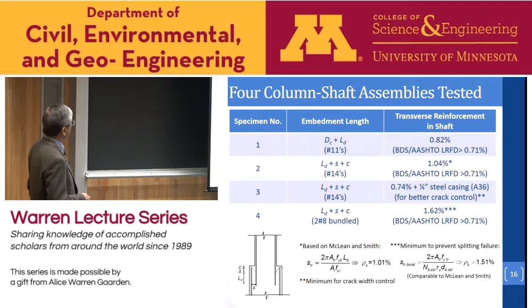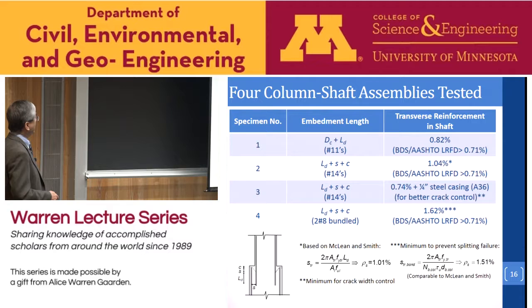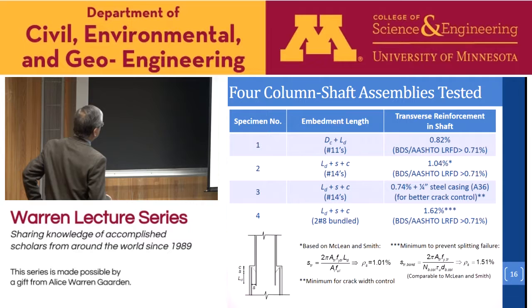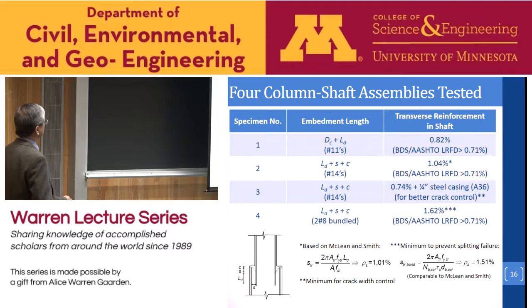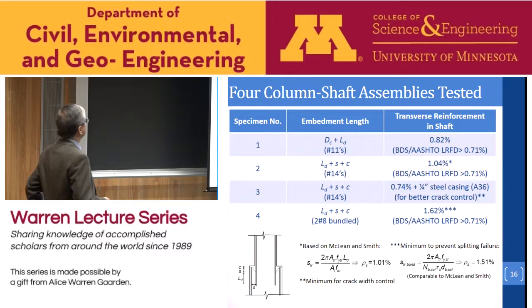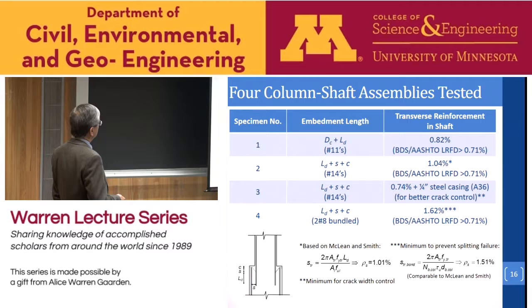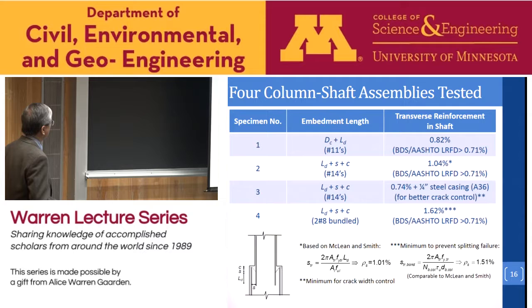This shows the embedment length used. They vary the embedment length. And also there's variation as to the quantity of the transverse reinforcement in the shaft, which is very critical because without appropriate confinement, we could have splitting failure of the bond and have premature anchorage failure develop, okay? Now, in the first specimen, we use a requirement close to the minimum required by Caltrans, which is essentially the diameter of the column plus the LD specified in AASHTO, okay? The other is what we recommend based on some other studies and also numerical simulation, and it is much lower than this one. It is the AASHTO development length plus S. S is the spacing of the longitudinal bars in the shaft and in the column, and C is just the concrete cover here. So this is based on the truss analogy, okay?